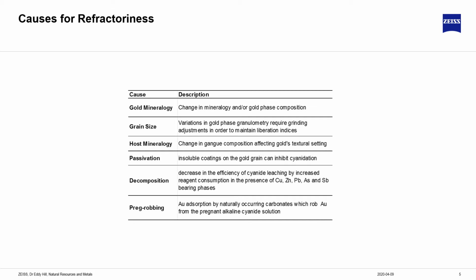Changes in grain size may require grinding adjustments in order to maintain the liberation indices. Changes in the gangue composition may affect the gold's textural setting, or the gold-bearing phase's textural setting. It may be that its mineral association changes, it's no longer associated with silicates, and now we suddenly find it encompassed within sulfides.